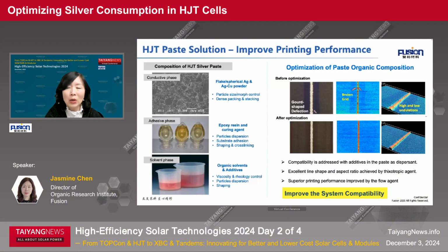With the narrow screen opening and faster and faster printing, we have a very challenging problem in HJT. The challenge is printing performance. It's very hard to get a very good printed line because it is narrow, so we need a solution to solve the problem. Our solution is to improve the compatibility. Compatibility is very important for very narrow openings and thinner lines. So how do we improve the system compatibility? We optimize the paste organic composition.